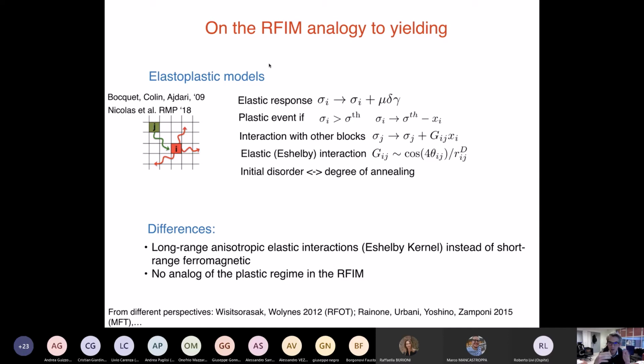And then, when you impose the deformations and deform the system, all these local blocks change the local value of the stress. If the stress goes above a certain value, which I call sigma threshold, sigma TH, then the system fails locally, so the stress sigma I goes down by a certain amount. And the loss of stress is redistributed among all the neighbors.